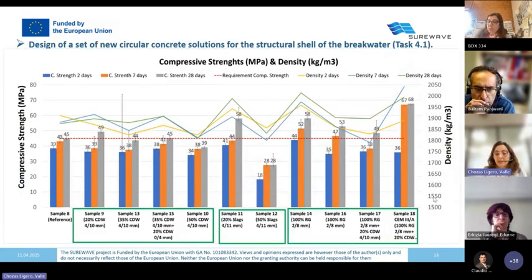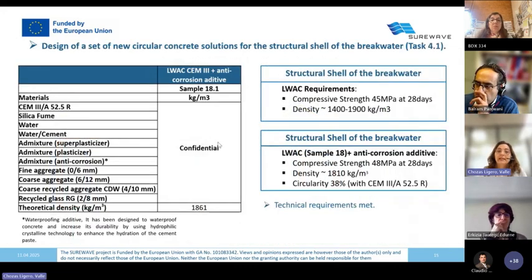Regarding concrete strengths, doses 14 to 18 are with recycled glass aggregates, and compressive strength was achieved in all cases. In this type of concrete, a new anti-corrosion admixture was also added in the optimized dosage to improve the durability. The results obtained for compressive strength, density, and a high circularity were good. Technical requirements were met with this type of concrete also.